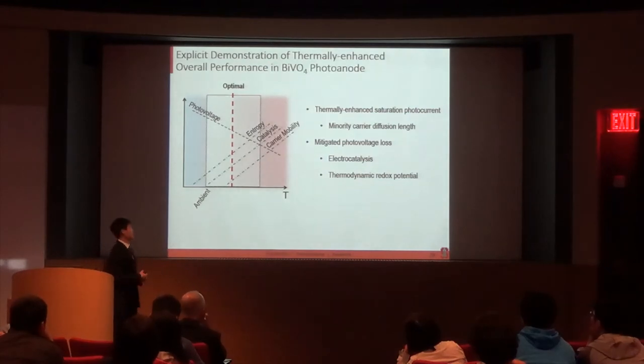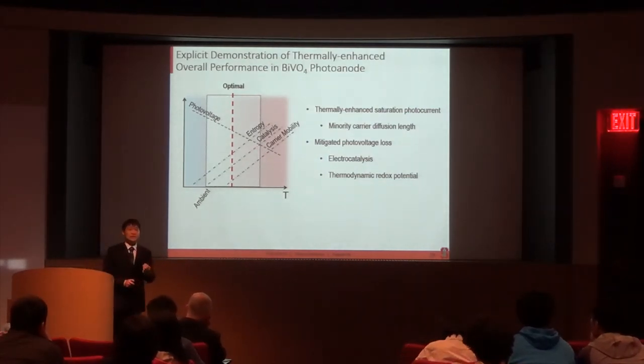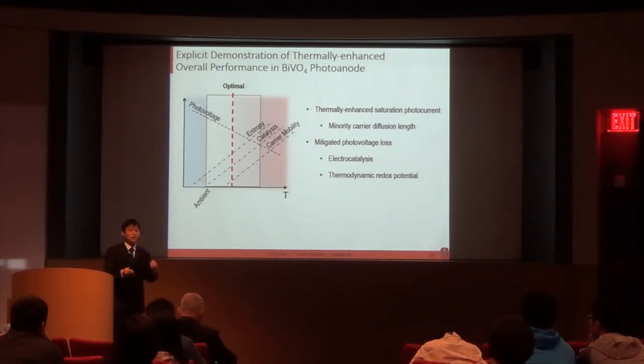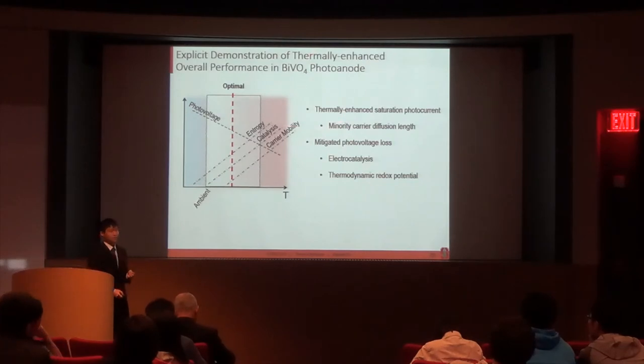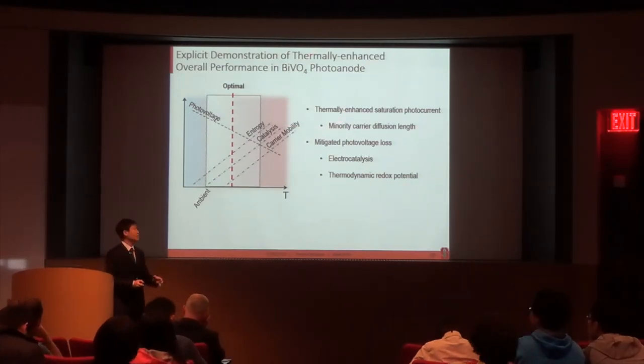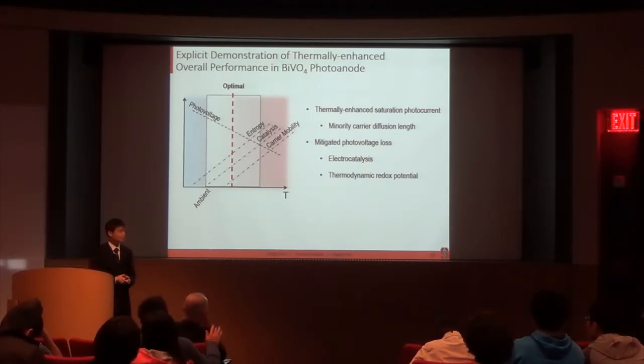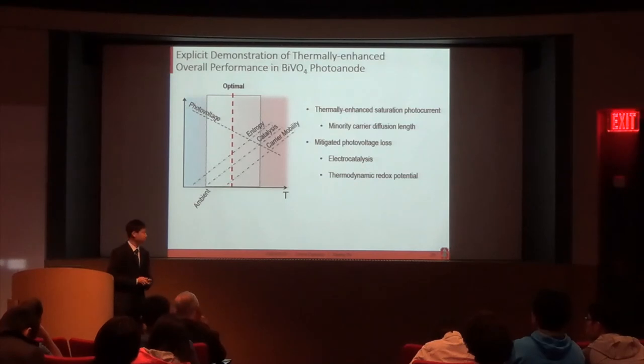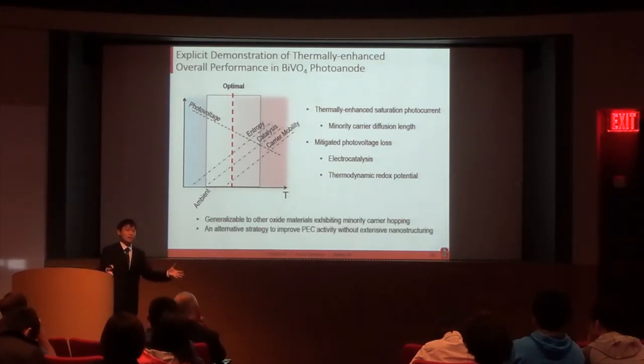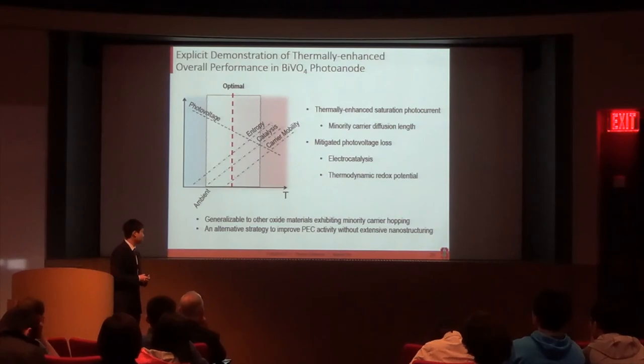So to briefly summarize, we have explicitly demonstrated that increasing the temperature could actually improve the performance in a BVO photoanode. The thermally enhanced saturation photocurrent can be attributed to the thermally activated minority carrier diffusion length, and the photovoltage loss is mitigated by the combined effect of catalysis and thermodynamics. So it is clear that the optimal temperature for BVO photoanode is above ambient temperature. And our strategy for thermal enhancement is actually generalizable to any oxide that exhibits hopping conduction mechanism. It also provides an alternative strategy to improve the PEC activity without extensive nanostructure.